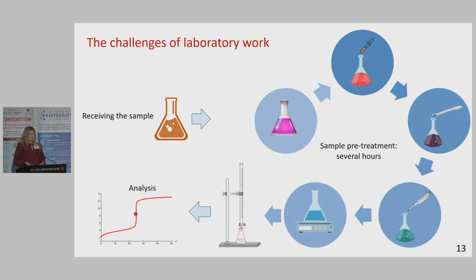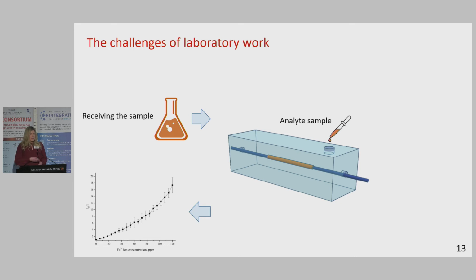Now, working in a laboratory is not always as exciting and fast-paced as it can be portrayed in movies and TV shows. A lot of times it's a very time-consuming and repetitive process. So for example, if I was asked to analyze how much iron I have in a sample, it would take me several steps to get to the measurement process. I would need to dilute the sample, adjust the pH, remove any impurities, prepare the solution for measurement, and only then I would get to the testing point and then to the analysis to determine how much iron I had in the sample. But if we were using the sensor we're developing, we're skipping all of these steps and going straight to the analysis and determining how much iron we have.